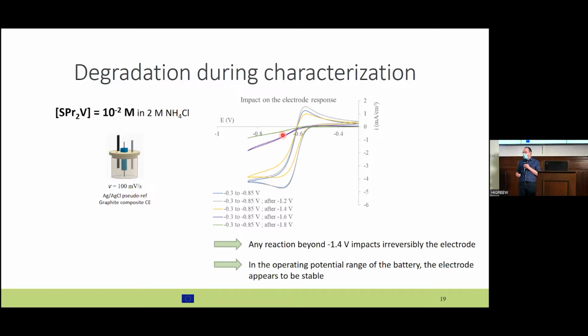So the loss of stability of the battery can come from the electrolyte. But in some condition, if the potential is not well controlled, there could be some irreversible modification of the activity. Here we lost completely the activity, but we use some conditions that should not be present in the battery operation.